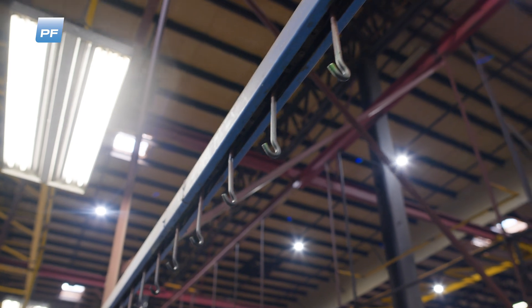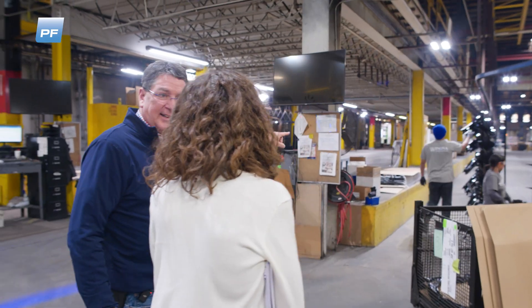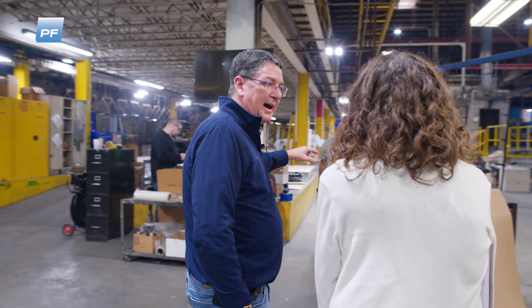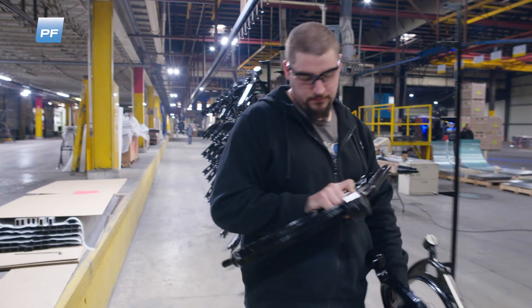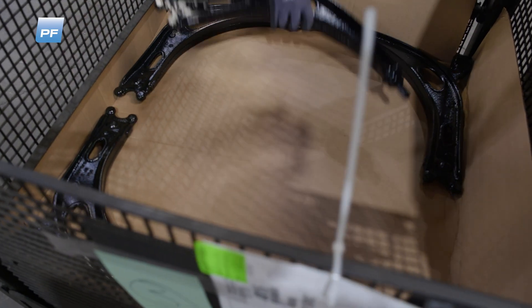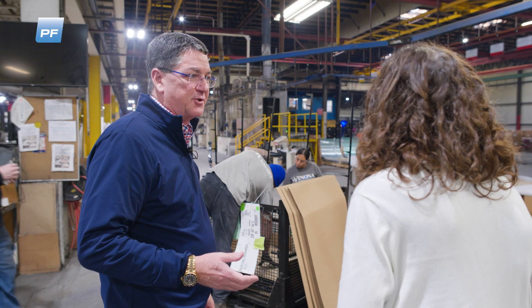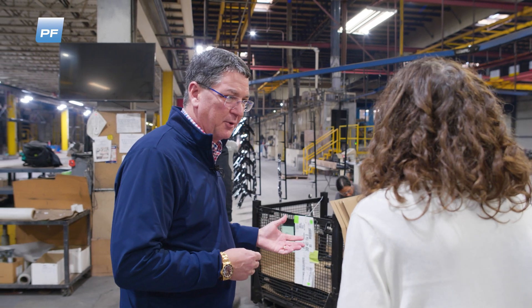This is the all-aluminum line, but the reason you're seeing castings — these are automotive parts — is these are E-coat primed, so they don't go through the wash system. What makes this an aluminum-only line is the chemistry in the washer. It allows us to get a more aggressive etch on the aluminum for a better bond, where we can't use that same chemistry if we're running bimetal, steel, or cast iron and aluminum through this.